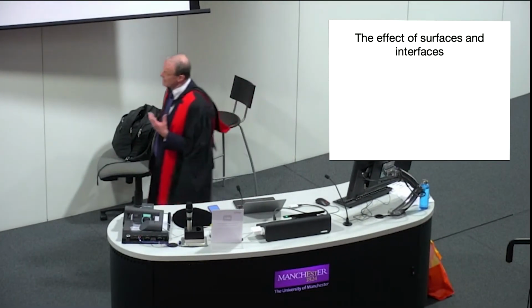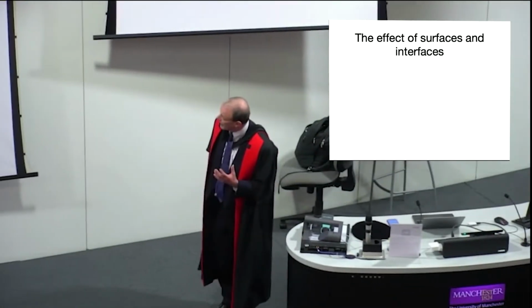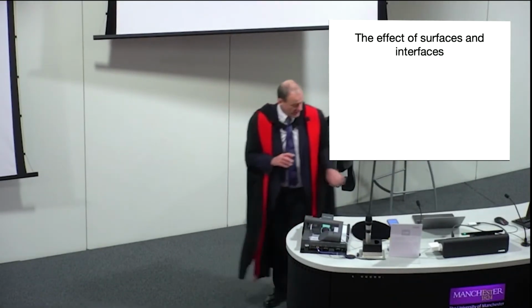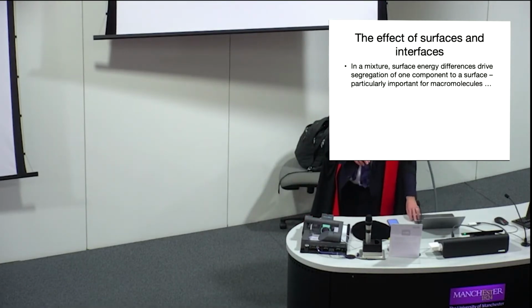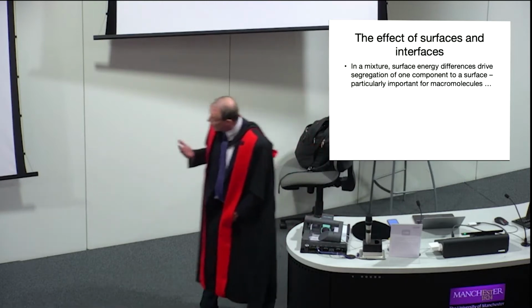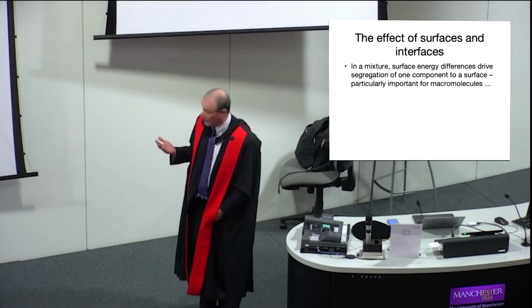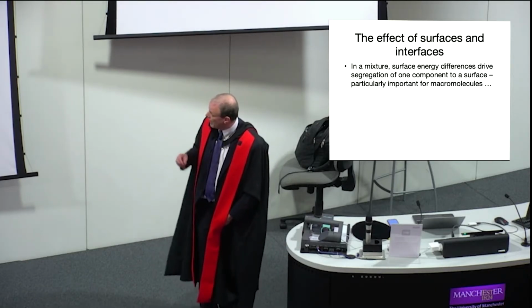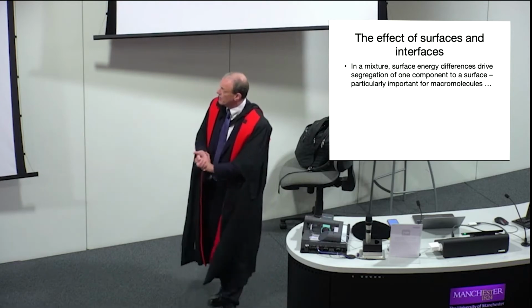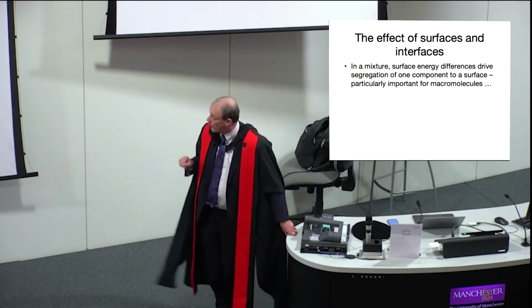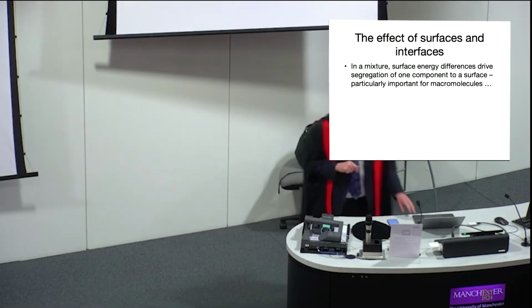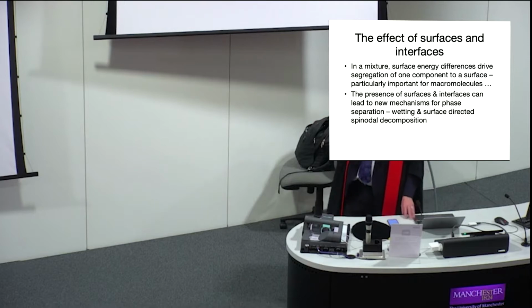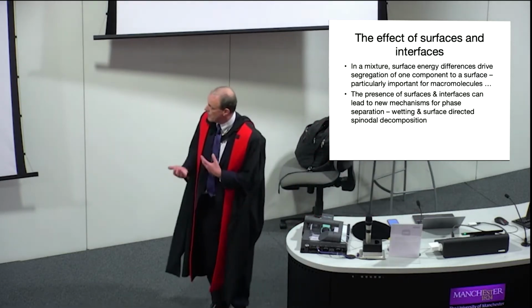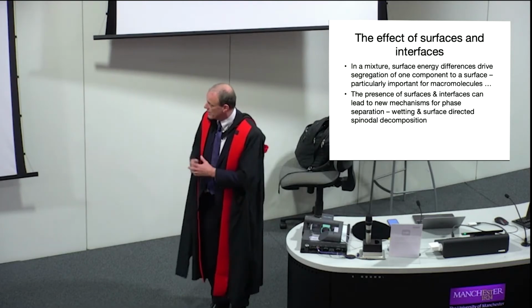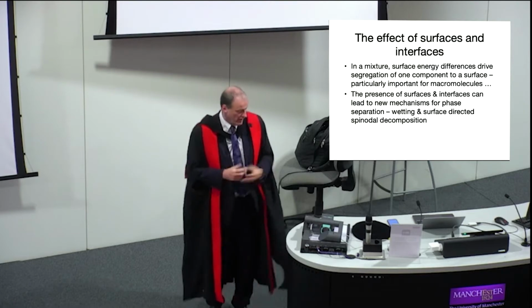So that's by way of background. What difference do having surfaces and interfaces make? Most of what I've done over many years has been to focus on the effect of surfaces and interfaces on this kind of process. And the first thing I'd say is, in a mixture, if you take two things, one of them is bound to have a lower surface energy than the other, just because that's the way things are, and you'd expect that to drive segregation of one component to a surface. And it turns out this effect is really important for macromolecules, much more important for macromolecules than for small molecules. And what we find is the presence of surfaces and interfaces can lead to new mechanisms for, say, phase separation. So wetting and surface-directed spinodal decomposition that I'll come to in a moment.